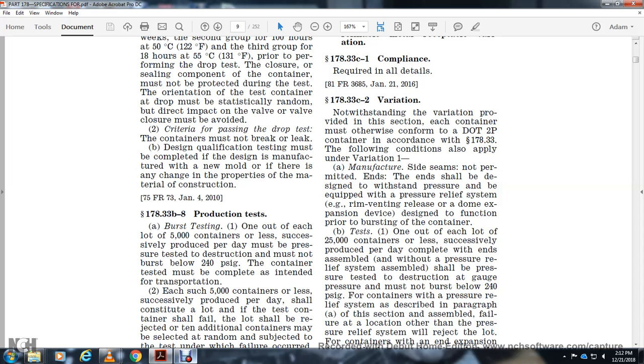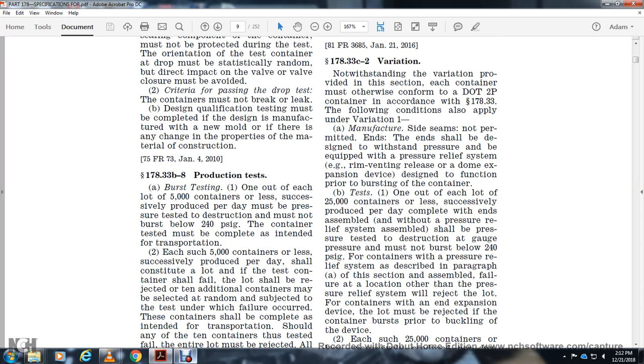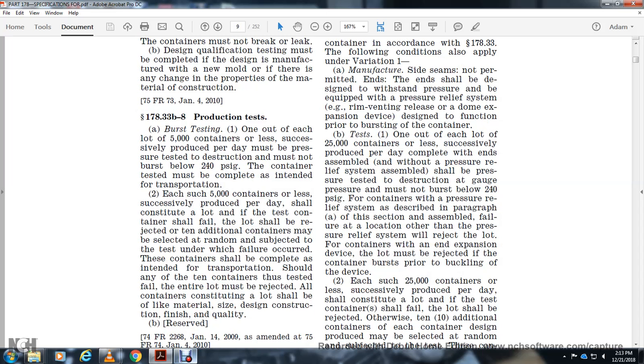Testing: one out of each lot of 25,000 containers or less successfully produced daily, complete with the ends assembled without the pressure relief system assembly, should be pressure tested. Under gauge pressure it must not burst at 240 psi gauge. For containers with the pressure relief system described in paragraph (a) of this section assembled, a failure at a location other than the pressure relief system rejects the lot. The containers with any expansion device lot will be rejected if the container bursts prior to the buckling device.